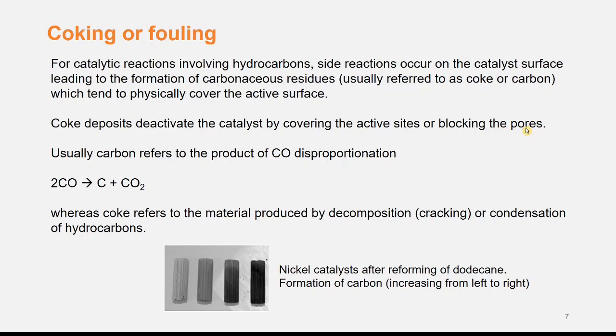There is a distinction between coke and carbon. Do you know what that is? Although we often use the terms interchangeably, strictly, carbon refers to atomic carbon, which comes from the disproportionation reaction of carbon monoxide, whereas coke refers to the deposits produced from cracking or condensation of hydrocarbons.